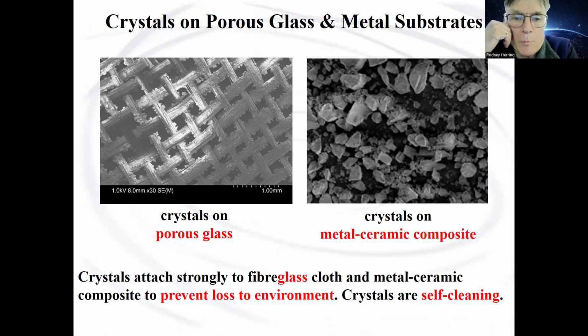We can put the crystals onto glass, and specifically, as we see in the left-hand side here, fiberglass, and you can see all the little crystals on it. Or we've learned how to stick them on to metal ceramic composites so that we can apply the crystals and not lose them to the environment. And the other nice feature about this is that they're self-cleaning.